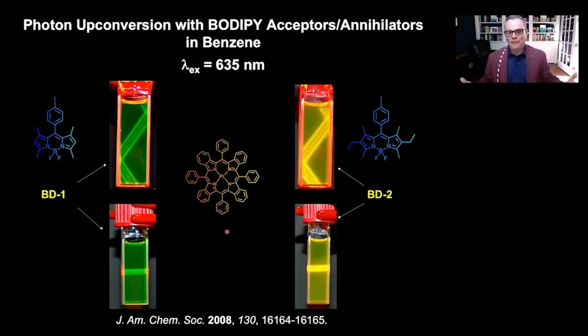And then it became obvious the next step is going to be, can we move things further to the red? So then we started to go to benzannulated porphyrins as sensitizers, and then we got creative. We said, we got to get away from aromatic hydrocarbon acceptors in all of these upconversion mixtures. So we started using BODIPY dyes, and both of these came from Raymond Ziessel, who collaborated with me on a number of projects for about 15 years. And you can see that we could do red to green, red to yellow. I mean, as I said before, these things photograph beautifully.